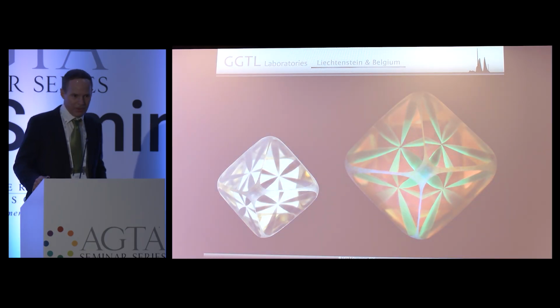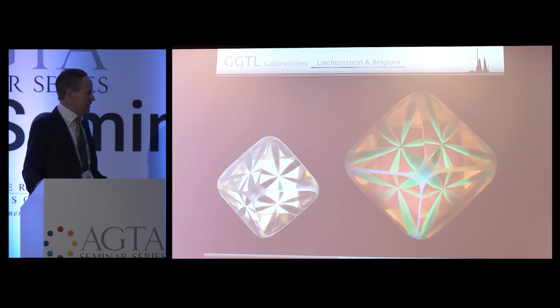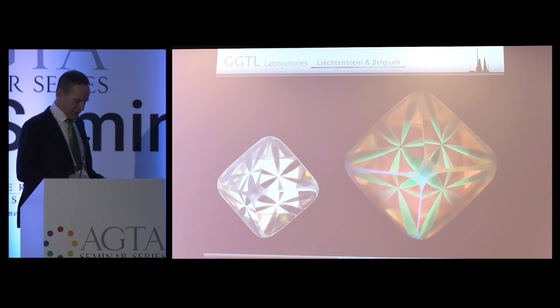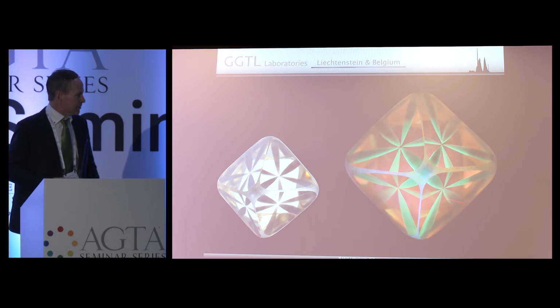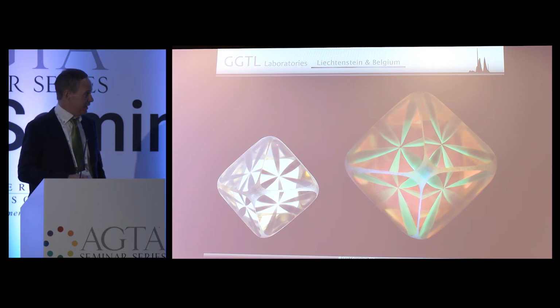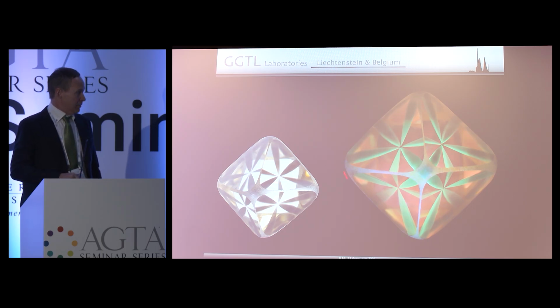This one, pretty well known. Rhodesian star, over 10 carats. In my opinion, still the best stone of this kind in the market. The pattern is absolutely stunning. So what you see here is the shape of the diamond itself is octahedral, as you can see. But these sectors that fluoresce green are cuboid. And you can tell here at the corner,